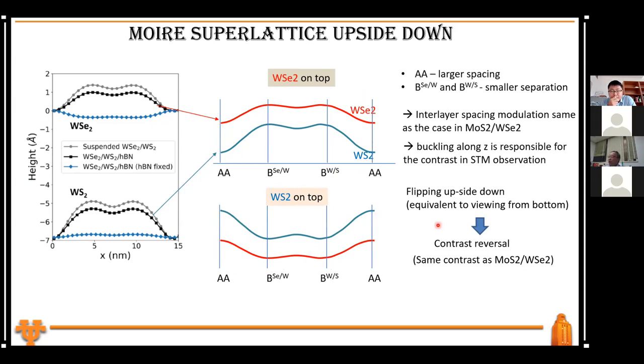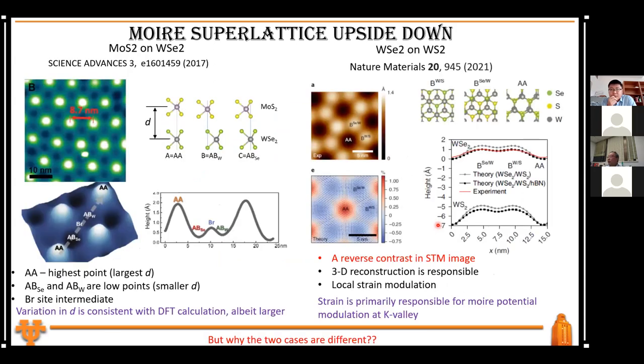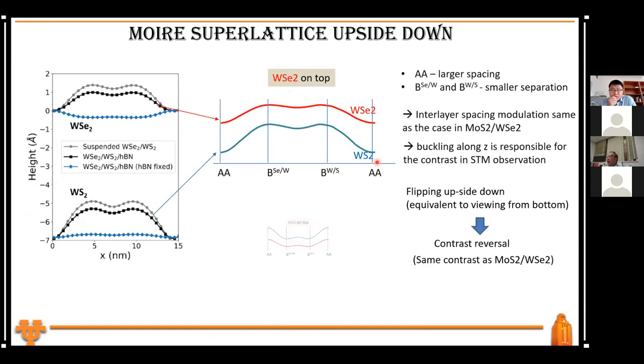So that explains why the two STM works will have the contrast reversal. That puzzle is solved, but it also provides us with a means to explain why the intralayer exciton moiré potential is so large. Because in that case, the moiré potential is not really dominated by this simple interlayer coupling. For the intralayer, it is dominated by this strain relaxation within the unit cell. But I do want to say that this is a strain modulation within a moiré unit cell. If you take the whole moiré, it is still zero total strain. It's just that one region goes positive, one goes negative. But that is enough to give rise to a very large intralayer moiré potential. And that explained our result.